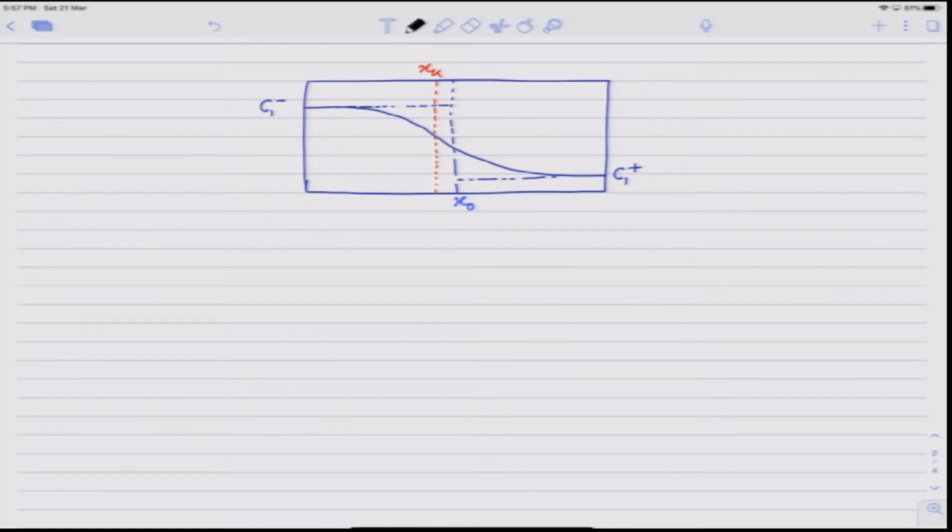Now we know we can write the intrinsic diffusion flux as J1 equal to J1 tilde minus C1 times Vk, where Vk is the velocity of the marker plane. Out of this we know how to determine J1 tilde directly from the concentration profile. So all of this we are considering at the marker position xk, because that is the only lattice plane that we are able to track, because the marker can be placed only at the initial contact plane.